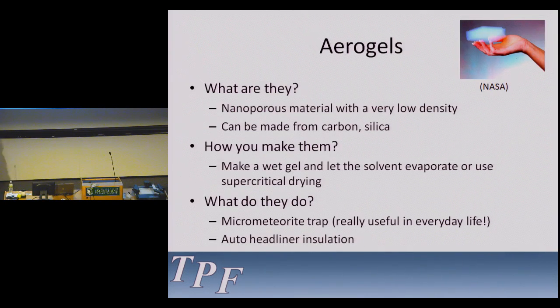Aerogels. This is another area that's nanoporous. If you've ever seen these materials, they look like solid smoke. And they basically are a very fine silica network. You can also make them out of carbon and other materials. You make a gel and let the solvent evaporate. And they were originally developed by NASA as micrometeorite traps, which are really useful in normal life.